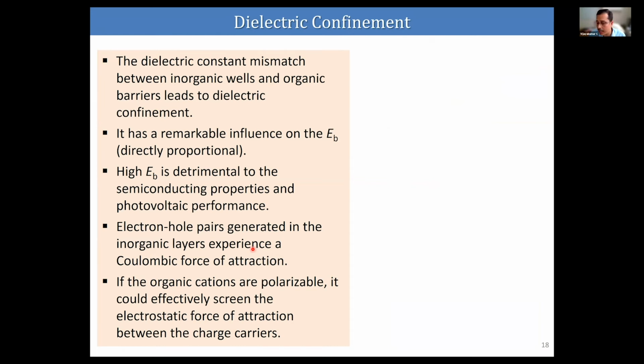We try to understand the dielectric confinement in these materials, and the dielectric constants of the inorganic wells and the organic barriers are hugely mismatched, because the organic components are not polarizable, and inorganic units are having charges, or are polarizable. Because of the dielectric constant mismatch, these materials show huge dielectric confinement in their properties. And because this dielectric confinement is directly proportional to the exciton binding energy, the exciton binding energy is very high in this material, and the charge carrier separation is very, very difficult in this material. So it is not suitable for photovoltaic application.